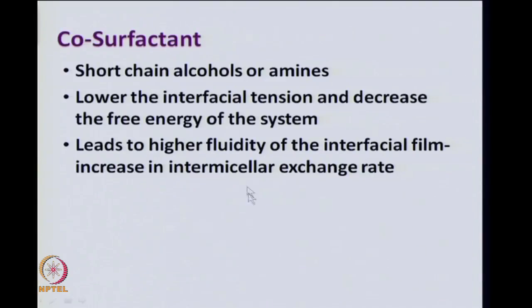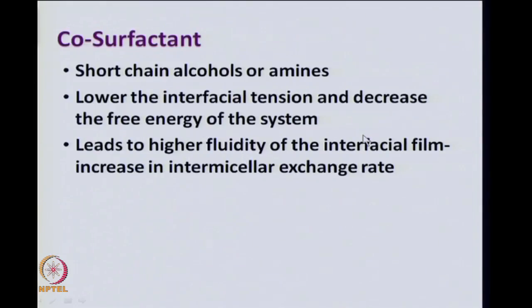So, the co-surfactants I already discussed, co-surfactants have short length, short chain alcohols or amines. They help the surfactant to lower the interfacial tension and they lead to higher fluidity of the interfacial film and increase in intermicellar exchange rate. So, the co-surfactants basically like we have used butanol or pentanol etcetera, help in decreasing the interfacial energy between the water medium and the non-aqueous medium, the solvent which we are taking, which may be isooctane or heptane etcetera.